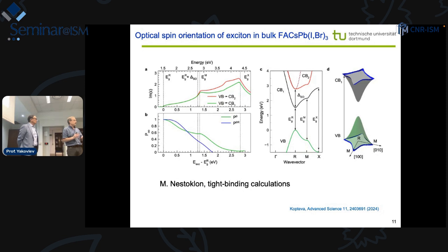Maybe for the internal degrees of freedom, but we need to look carefully at this. So FA or MA or PEA, it seems that they do not contribute too much to the electronic states, like for the electrons and for the holes, for their localization. The coupling with the nuclei does not come from these, for example from cesium or from these organic materials. The main contribution from nuclei comes from the lead, which is present everywhere.